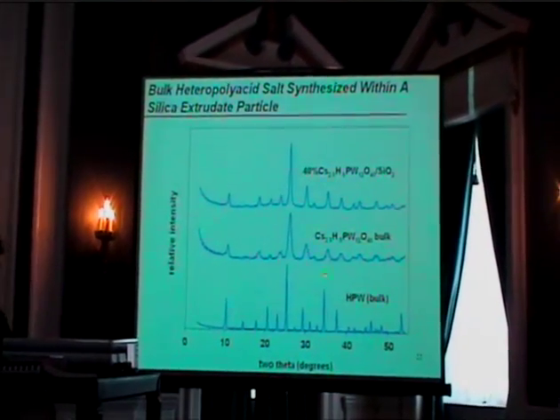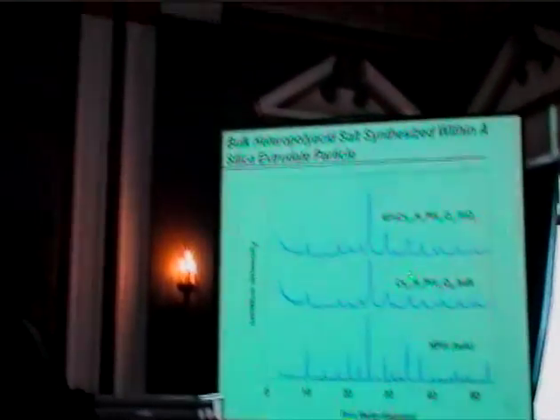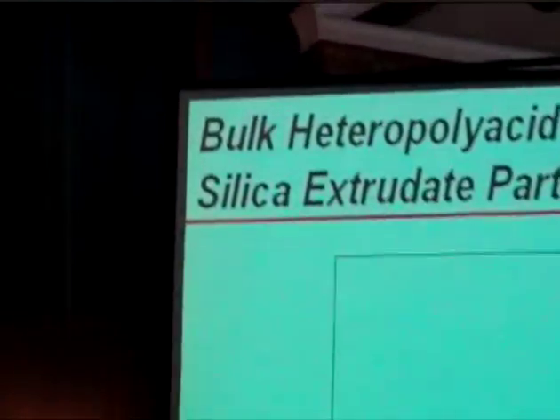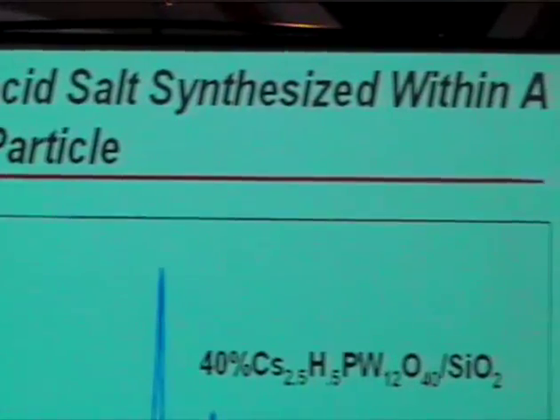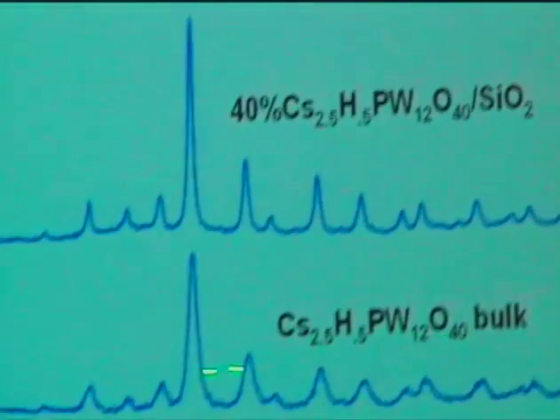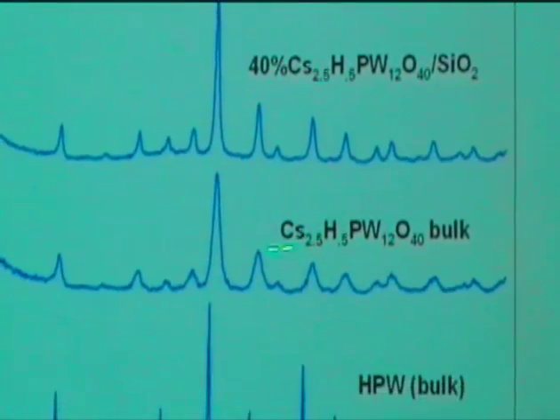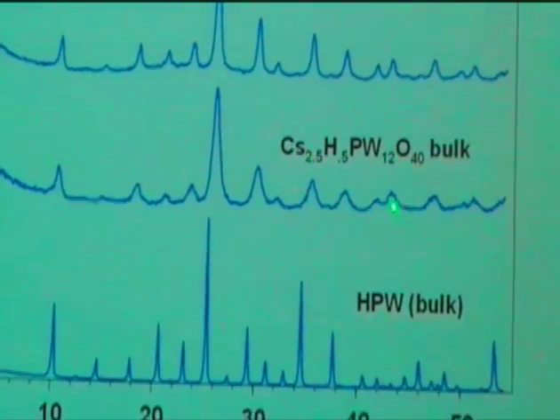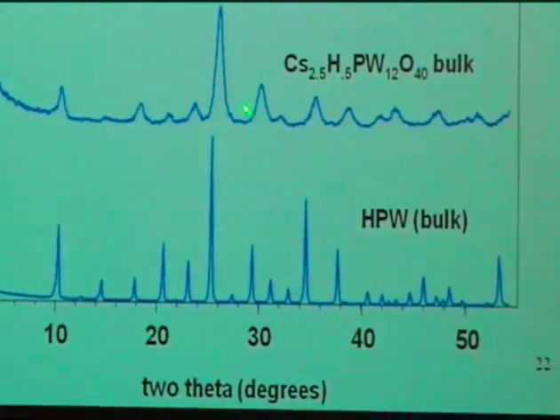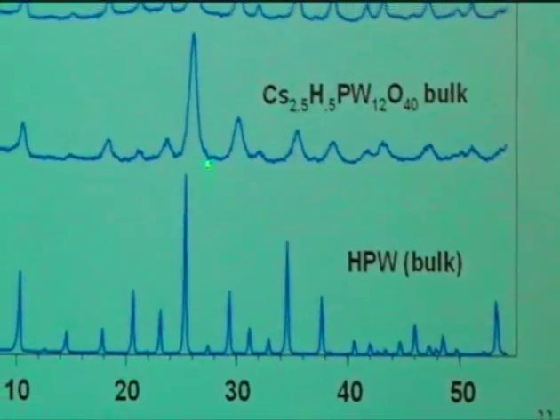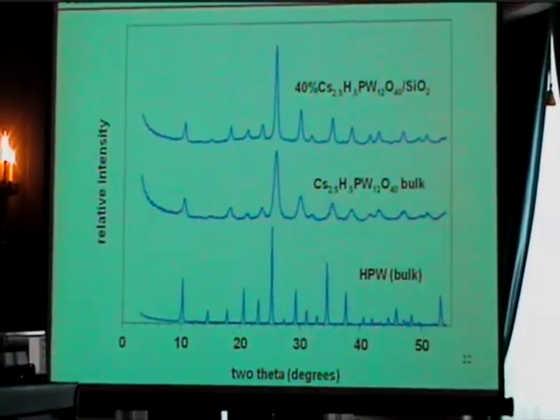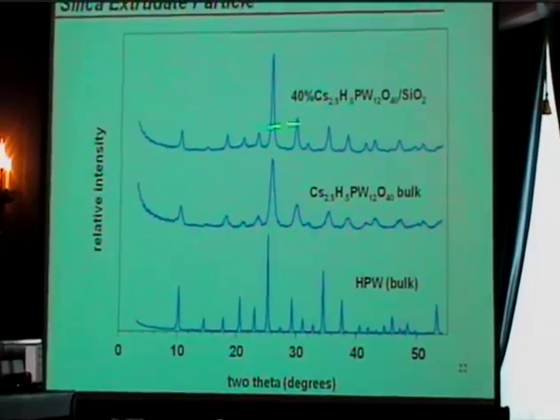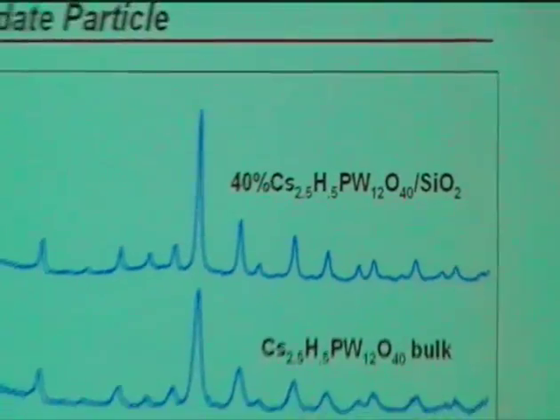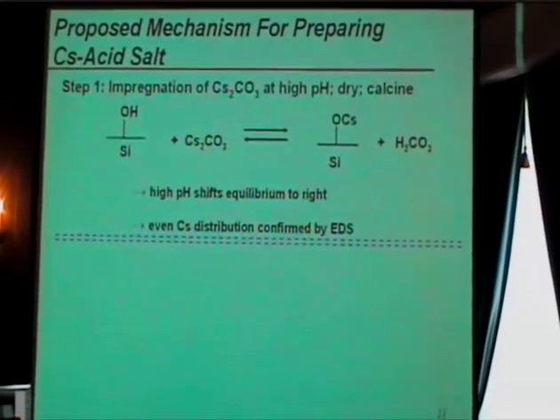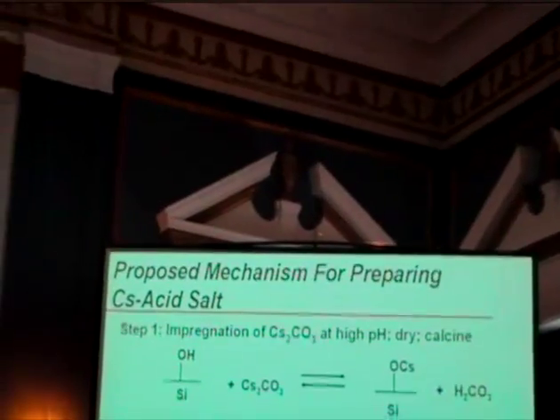Okay, let me first show you a little bit of evidence that is what happened. This is an X-ray diffraction of the phosphotungstic acid, nice cubic pattern. If you just precipitate and make the bulk cesium one, you see two things. One, the peaks have shifted to higher angle. The unit cell is contracted because the cesium is smaller than the H5O2+, and they broaden because the particles are so small. This is what we get when we take those extrudates and grind them up. You see exactly the same thing. Okay. So both the EDS and the X-ray confirmed it.